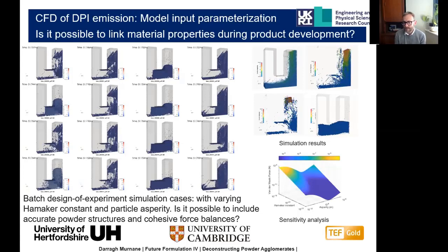And you can see from the simulation results on the right that yes, we are able to simulate effectively the chaotic and the fragmentation behavior of some of these cohesive powder mixtures. But we're now also able to start building in different powder cohesion forces. So the real trick is whether it's going to be possible to include accurate powder structures rather than simulated powder structures, and cohesive force balances. So if we can take our laboratory measurements of surface energy forces, can we build that into the powder cohesion model to try and model better the fluidization and aerosolization events?